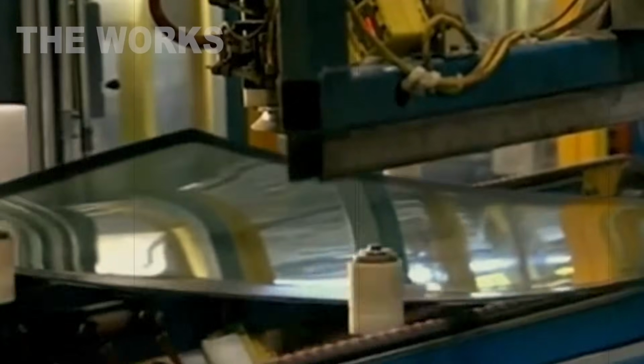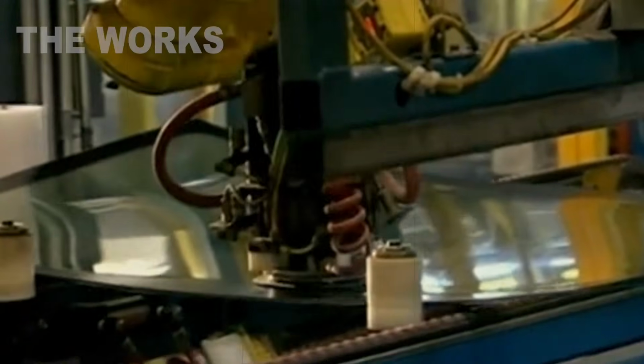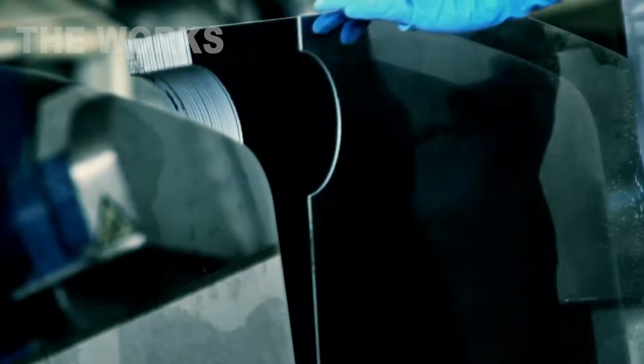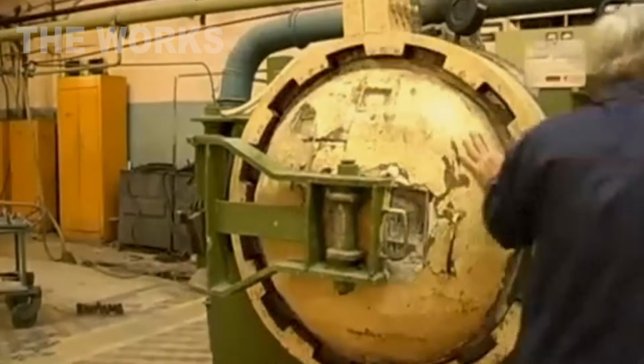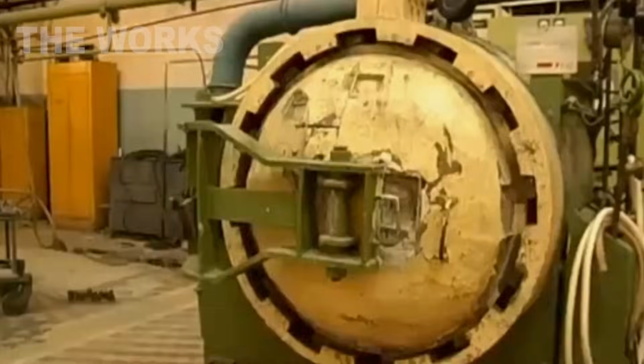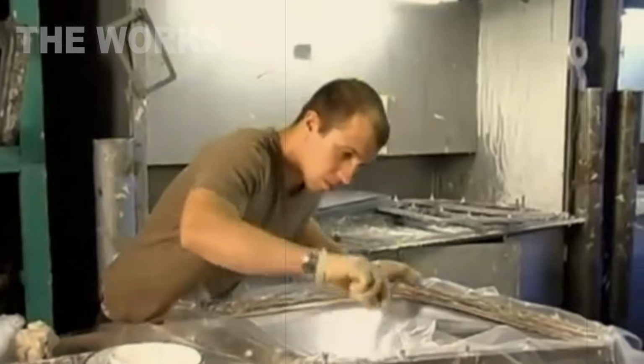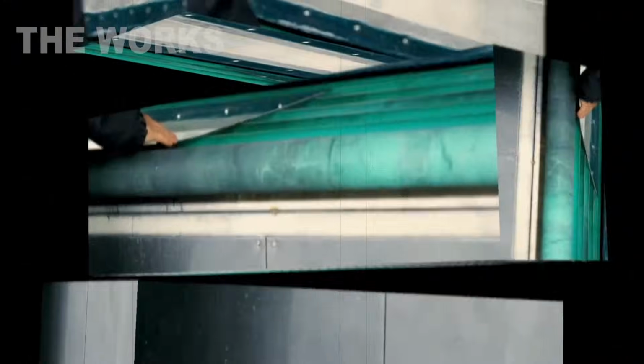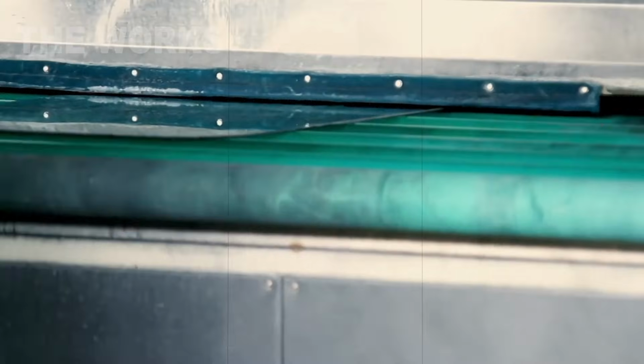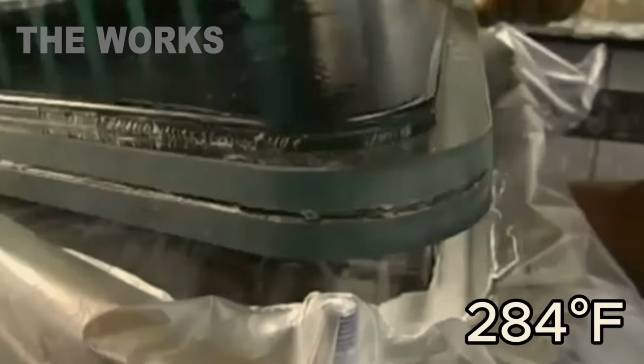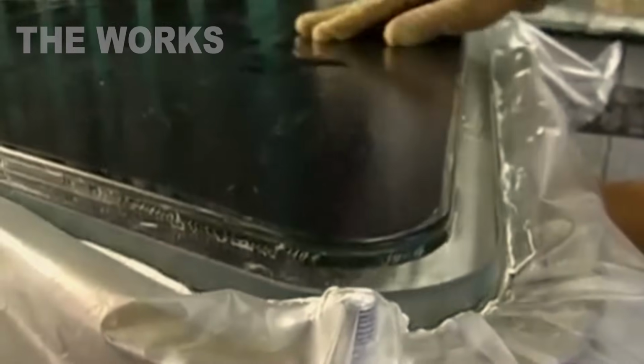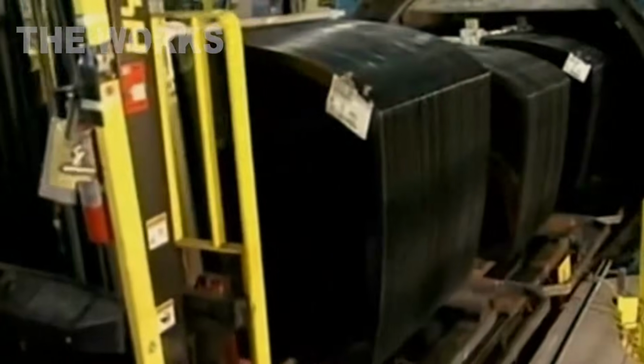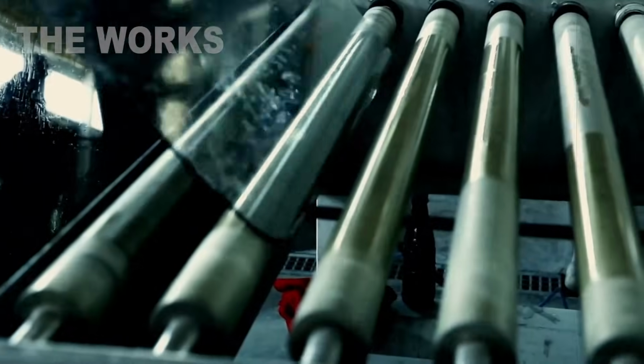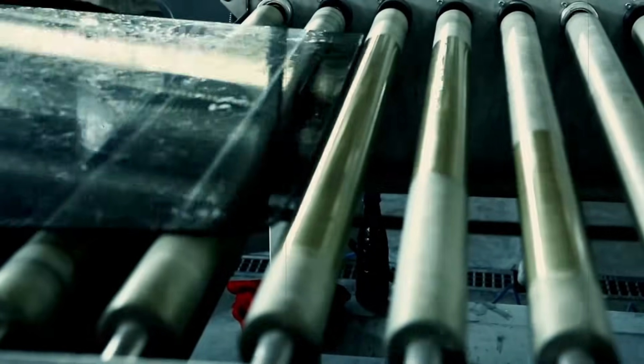Windshields use laminated glass, a construction of glass and polymer film. Its manufacturing involves several steps. A polymer film is placed between 2 glass sheets. The construction is put into a vacuum press to eliminate air bubbles. Next, the glass is heated in an autoclave to 284 degrees Fahrenheit under high pressure. This creates a rock-solid bond between the layers. Laminated glass has exceptional impact resistance, and when damaged, it stays held together by the polymer film, keeping drivers and passengers safe.